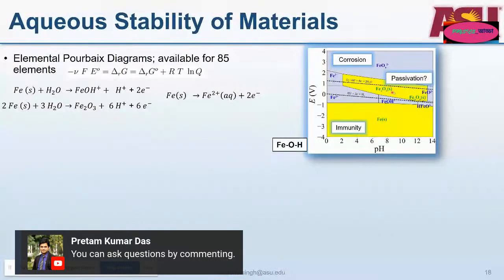And this Fe2O3 could form on the surface of iron, and it could potentially form as a barrier for further reaction of the water with the iron. Or it could be porous, and then it could still allow the reaction of iron continually, changing the whole iron to iron oxide. So it could potentially be a passivating film.